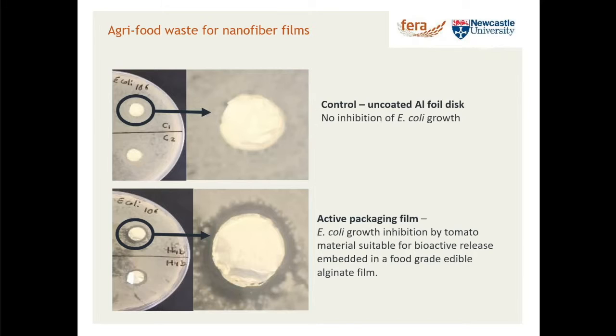One of the things we can quite easily demonstrate is whether or not these materials have any kind of inherent antimicrobial effect. And certainly this is often the case. We can find that if we take a little piece of material, stick it onto an agar plate where we've seeded with bacteria, you find there's often a zone of inhibition around the disc. So what this is showing is that the disc material, the fiber film that we've spun, has an inhibitory effect. And again, if we incorporate food waste, such as tomato skins or other materials which have antimicrobial activity, we see these sorts of zones of inhibition, as they're called, around the disc. And this is our control showing no inhibition at all. So this is demonstrating inhibition of E. coli based on nanofibers, in this case, this is alginate, in which we've embedded dried processed tomato skin.